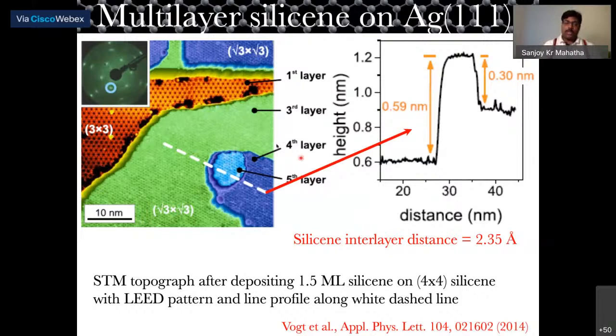This has an sp2 layered structure, so it is basically multi-layer silicene, like multi-layer graphene or graphite, with this sp2 kind of hybridization. But from the STM topograph, what they found is that the jump of this single silicene layer is around 3 angstrom, but ideally it should be 2.35 angstrom, which they didn't find.